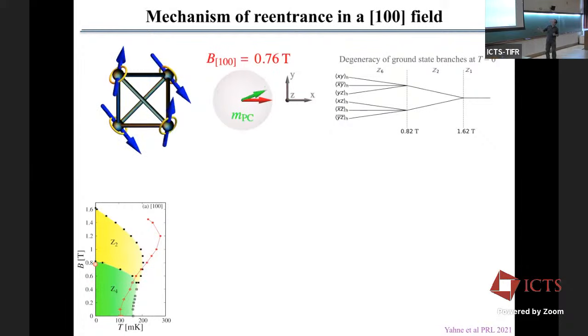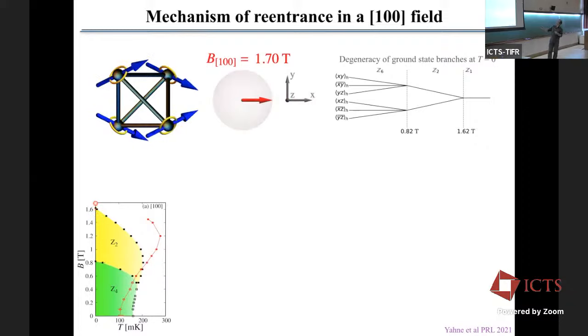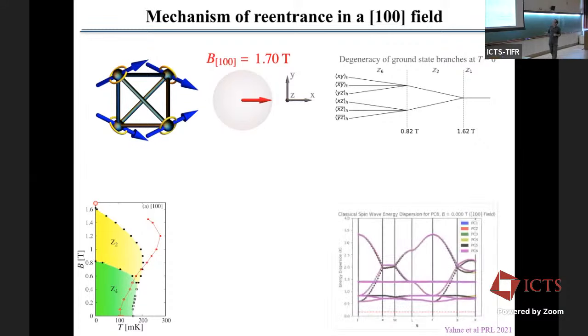So at low field, you have 6 degenerate states, but as you increase the field, these 6 states become less degenerate and they form only 2 degenerate states because they merge 3 by 3. And at higher field, you only have 1 state, which is a polarized one. And the thing is, at this transition temperature, what happens, if you do spin wave theory, you can see that